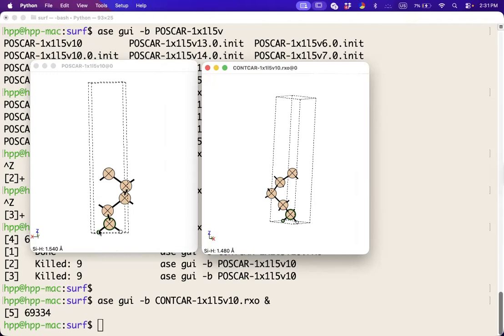And also look at the angle, right? The angle is also different. The original was 109 degrees, and now it is 102 degrees. So you see, as I mentioned, these hydrogens were allowed to relax. In that way, we passivate this structure efficiently, so the hydrogen might think that this is a perfect crystal structure.